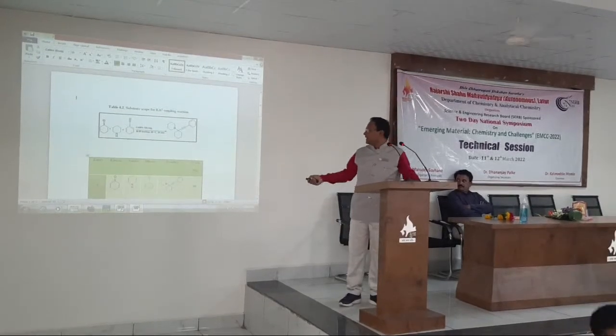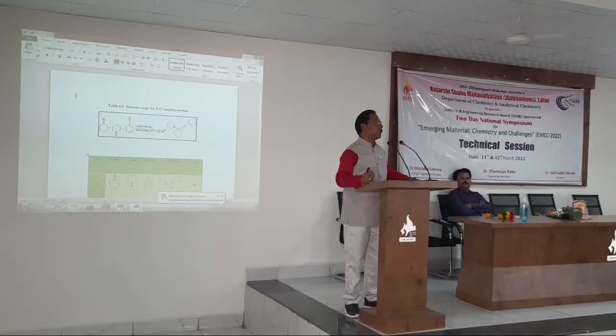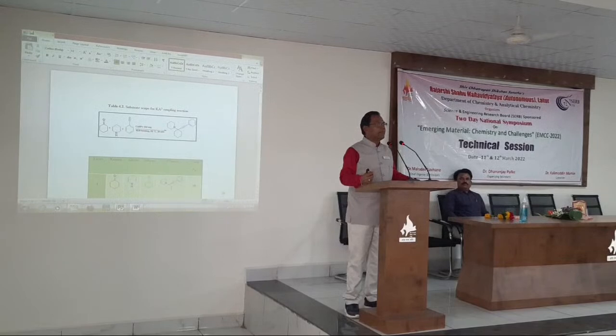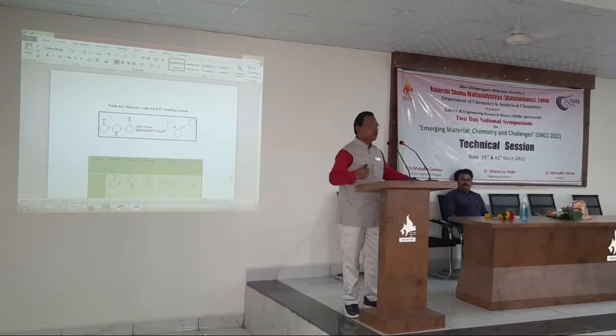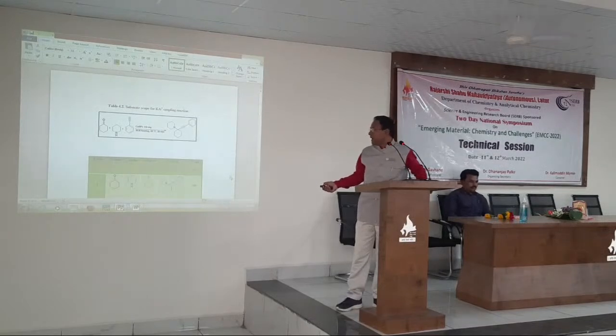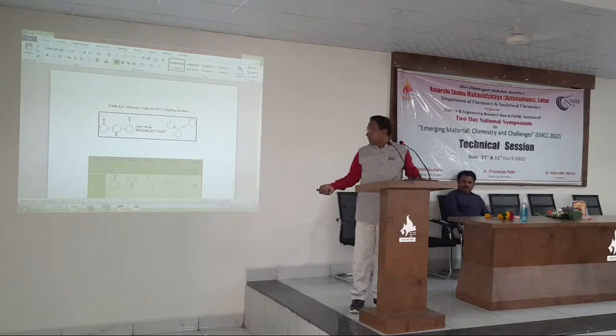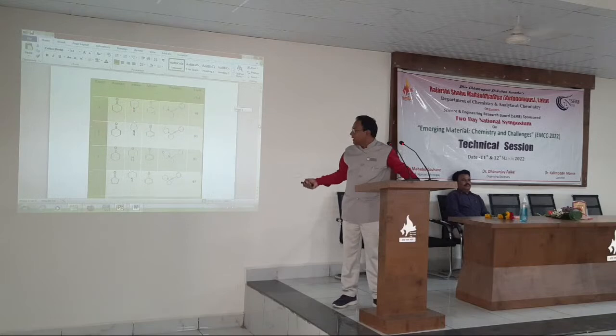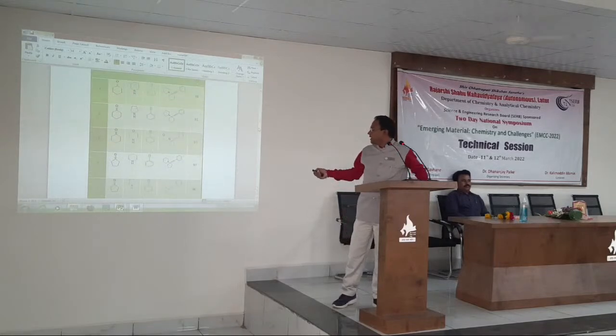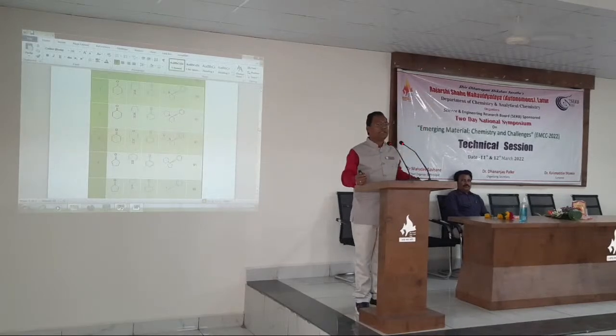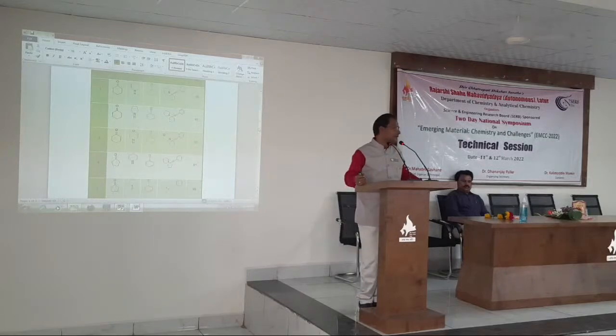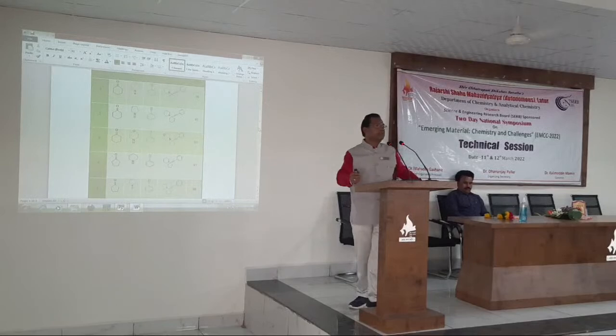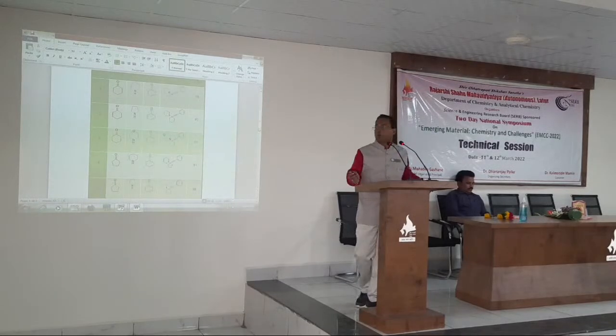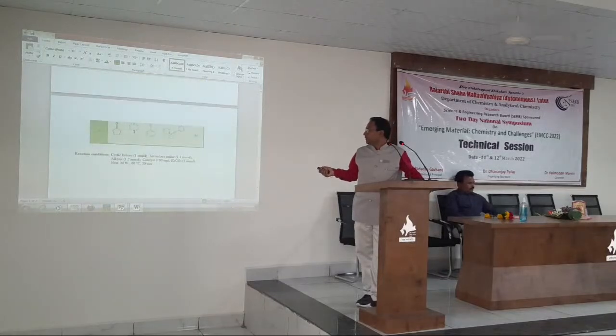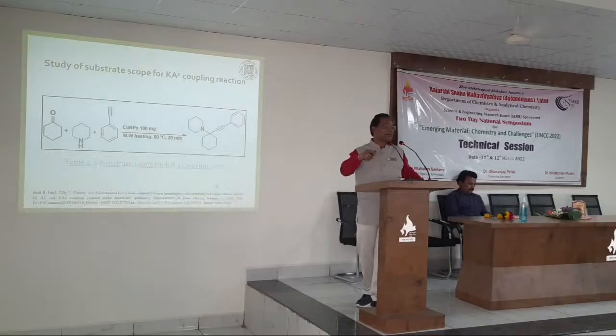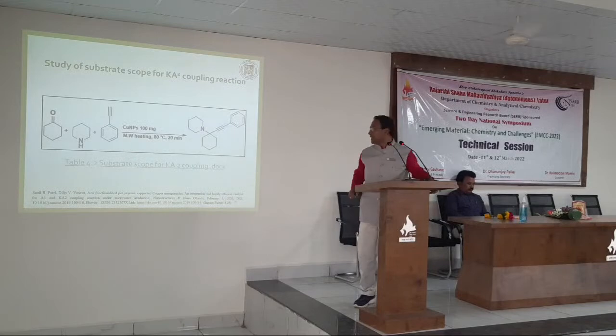Yes. So this is the reaction, and it was optimized, because this is the procedure for optimization of the reaction. So that is the research point of view. I am showing you that you have to optimize by taking the ketone and amine and alkyne, and in that you can have the derivative of the ketone, the derivative of the amine, acetylene, and in that way you can report the yield. In the original reaction, it was reported around 67% yield, whereas we have reported 98% yield with the help of the nanoparticles. And it took only 20 minutes. So within that 20 minutes, this reaction was completed.